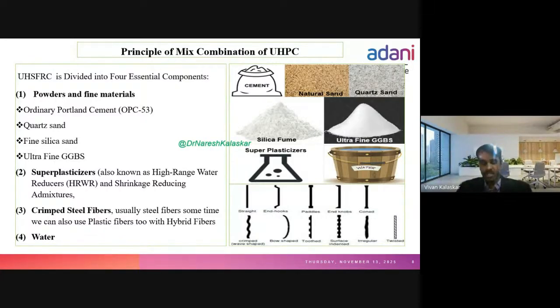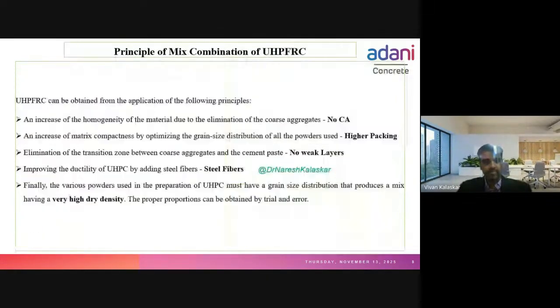And crimped steel fibers. Steel fibers are very important in UHPC, because in UHPC, if you take these high strength concretes, there will be a lot of shrinkage. And these crimped steel fibers reduce the shrinkage. They also improve the flexural behavior. So crimped steel fibers also play a major role. And water is very, very important to make the mix.